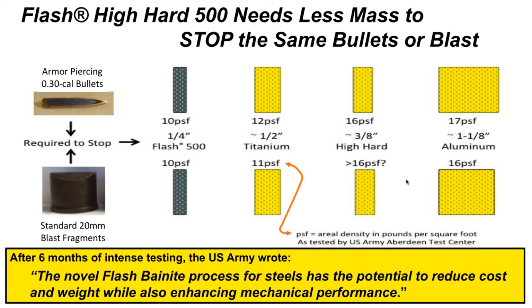Then, they already had data, so we made the comparison charts to match the performance of 10 PSF of flash against armor piercing bullets. 12 PSF of titanium armor was needed, 16 PSF of high hard, and 17 PSF of aluminum. So that's an interesting concept, since aluminum is supposed to be the lightweight armor, and titanium is supposed to be higher performing than steel, yet we've got a steel that's significantly lighter.